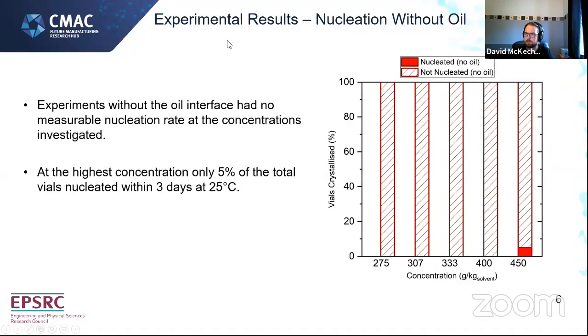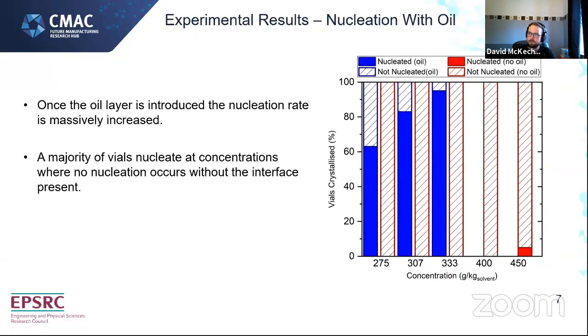Without oil present, we investigated concentrations from 275 to 450 grams per kilogram and observed very little, very slow nucleation. No nucleation occurred at all until 450 grams per kilogram, and even then only 5% of vials nucleated within three days. Once a layer of tridecane was added, we saw a significant increase in nucleation rate, with a majority of vials nucleating within the three-day period at concentrations where no nucleation had been observed previously — clearly showing the interface has a significant impact on nucleation behavior.